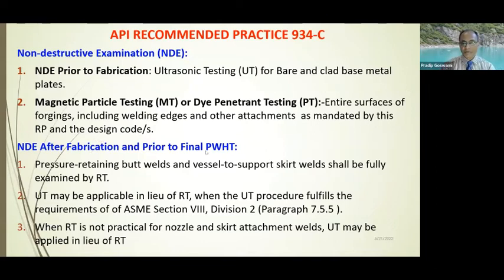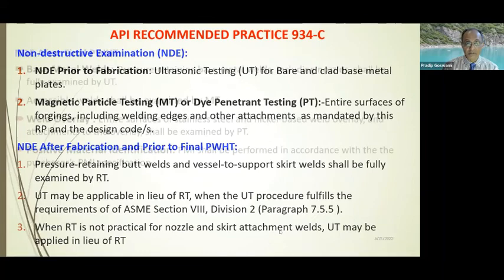NDE after fabrication and prior to final post-weld heat treatment: the final pressure retaining welds, the butt welds and skirt welds, should be fully examined by RT. UT may be applicable in lieu of RT, where the UT procedure fulfills the requirement of ASME Section 8 Div 2 paragraph, this particular paragraph. So UT and RT are kind of complementary NDE methods, and depending on the resources you have, you have the flexibility of using both, provided you meet the project as well as the design code requirement. When RT is not practical for the nozzle and skirt attachments, UT definitely can be a replacement, or an optional method in lieu of radiography or RT.